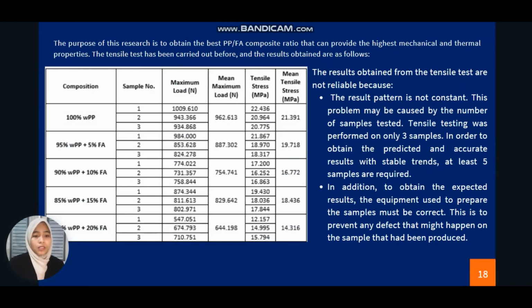So based on the slide that we showed, there is a table. Actually, this is a preliminary result that we had gained. But the result obtained from the tensile test is not reliable because the result pattern is not constant. This problem may be caused by the number of samples tested. We only used 3 samples for the tensile testing. Actually, to get the best result, we need to test 5 samples. So that is one factor why the result is not reliable.